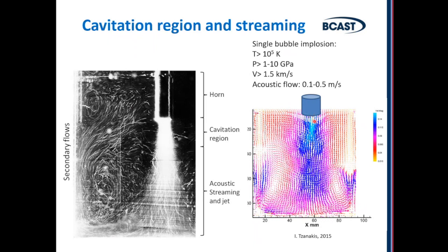While here, the processes are very quick, but also very high speed. When you talk about the implosion of a single bubble, I didn't mention this: when a cavitation bubble is created, it also pulsates in the acoustic field. Because it has a certain resonance size, after a few cycles of pulsating, it collapses, it implodes. And when it implodes, it creates in the center huge pressure, which also results in a huge, but very short in time, increase in the temperature. The velocity of this implosion is around 1.5 kilometers per second. So this happens on the scale of a single bubble. But in the bulk volume, the velocities of the flow are much slower.